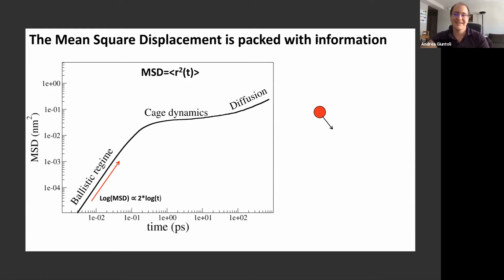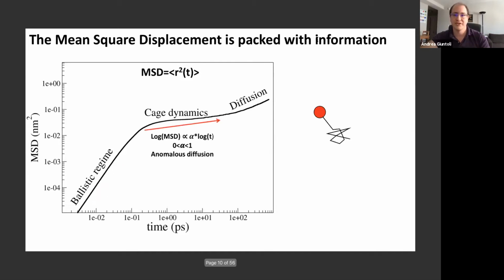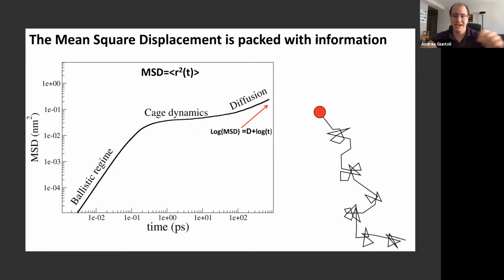And you get this behavior until the particle starts bumping into a solvent, other particles, or a structure. So it starts moving erratically, trying to find the best way to move ahead, to get out of this cage. So this is the kind of movement you see, and you see this anomalous diffusion. And then eventually it manages to escape this cage, and it finds another one, and so on and so forth. And averaging over long time scales, you see this diffusive behavior.